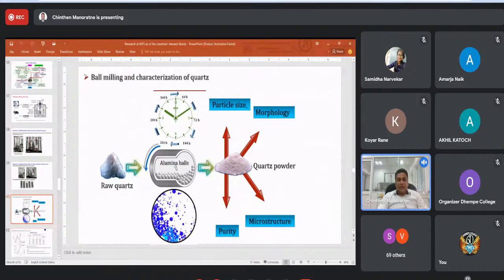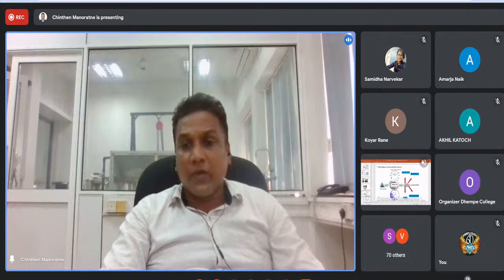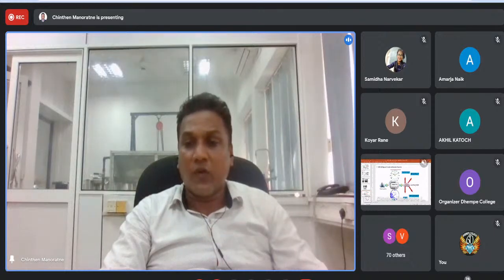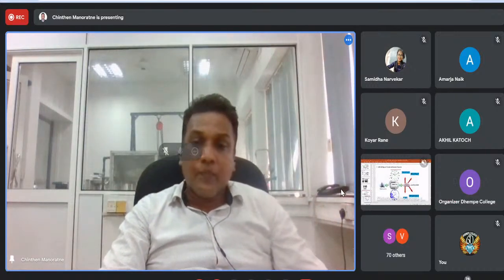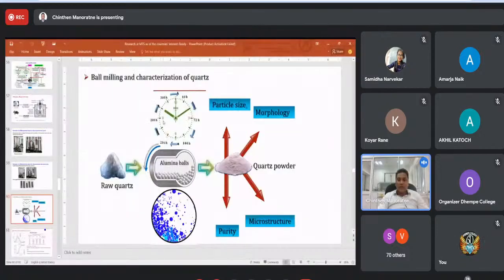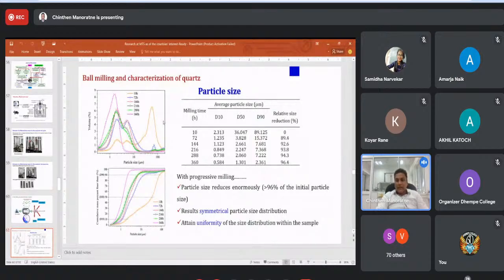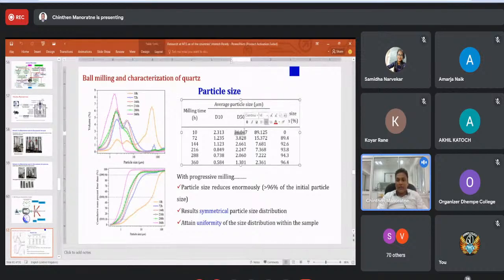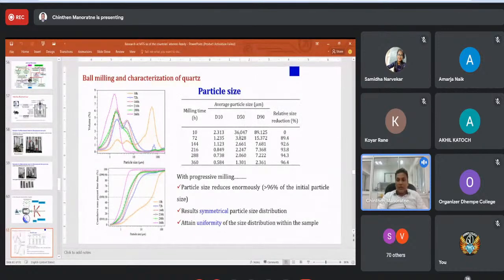So this is our basic preliminary study for quartz, and we studied their particle behavior when you reduce the particle size and their microstructure using particle size analysis, morphology, and so on. And we use ball milling for reducing particle size and optimizing their properties. And you can see when you ball mill quartz for 360 hours, you can reach 96% particle size reduction. You can see this is the corresponding particle size. The average size was 36 and it has been reduced to 1.3 micron.